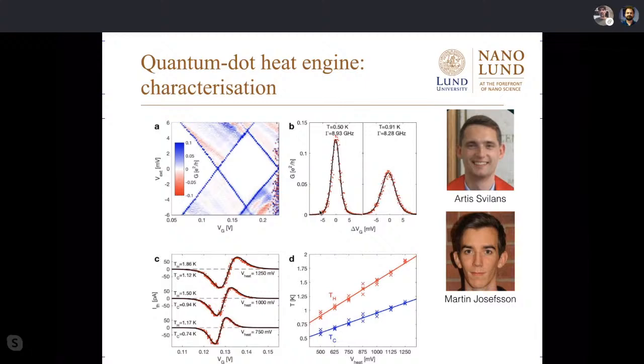We can measure the power produced by the quantum dot, but to get an efficiency, we also need the heat flow through the quantum dot, and we're not able to measure that. So the only game plan we had then was to measure the power and then have a quantum dot that is so well behaved and so clearly in agreement with theory that people and we ourselves will be able to believe the calculated heat current and use that for our efficiency. So that's why we wanted this perfectly behaved quantum dot and a perfectly matching theory.